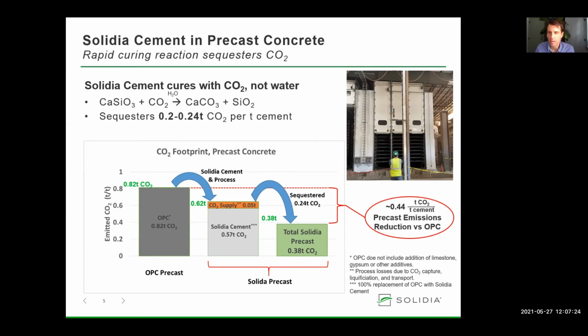In the presence of CO2 and a small amount of water that serves as a solvent for the carbonation reaction, calcium silicates are converted to calcium carbonate and silica. The products are stable and impart excellent properties to the final product. During the carbonation reaction, up to 0.24 tons of CO2 are sequestered per ton of cement. This reaction is rapid and goes to completion in hours, not days like in the case of OPC.